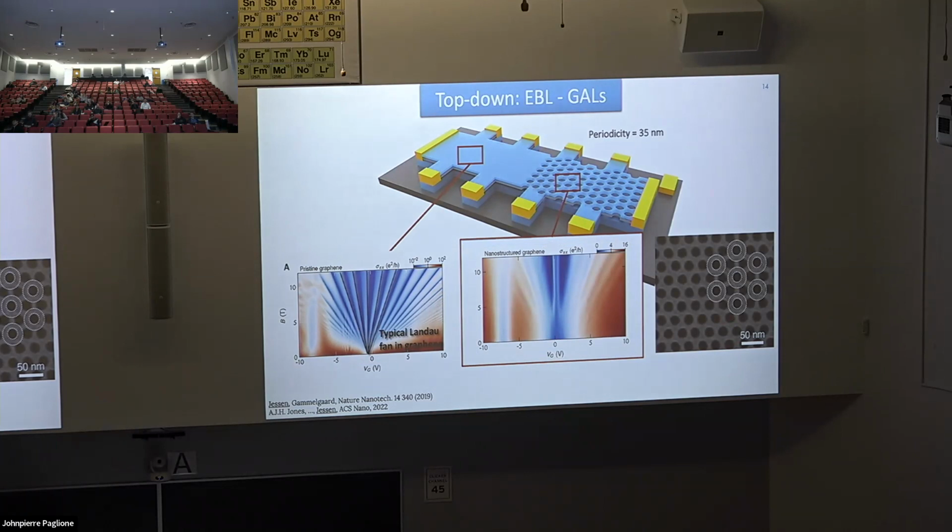And then if we compare that to the part of the graphene where we punched holes, so we tried to change the band structure into something where there's a band gap, suddenly the situation is quite different. These energy levels that always intersect 0 and are straight lines are now curved, intersecting at non-zero. And this blue region here for low magnetic fields, that's low conductivity. So that's actually the presence of a band gap that then changes as you turn on the magnetic field. And this is complex behavior that is hard to have a hand-waving understanding of, but it all matches theory.